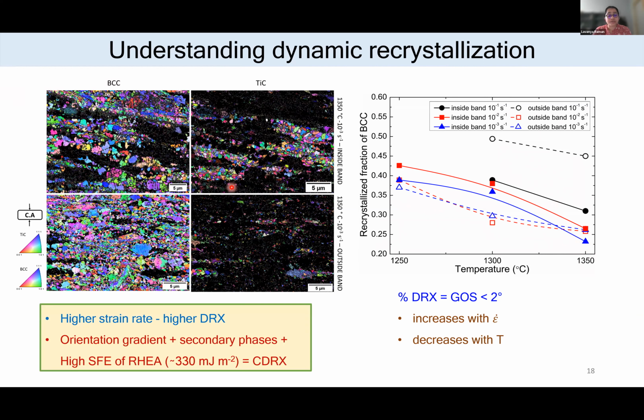And also when we combine this GOS analysis with the secondary phases that we have, and also with the high stacking fault energy of this HEA, we can confirm that what's happening in this alloy is a continuous dynamic recrystallization. That is one thing which we'll have to understand. So it's not like a conventional, discontinuous dynamic recrystallization. The presence of secondary phase and the orientation gradient within each BCC grain results in this CDRX.